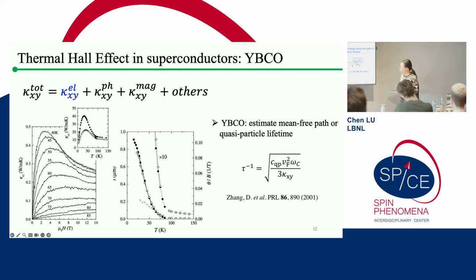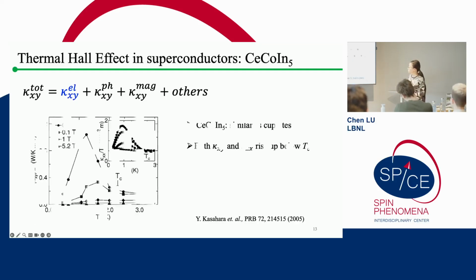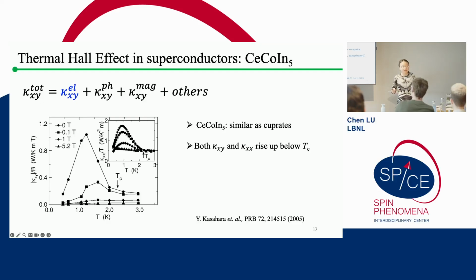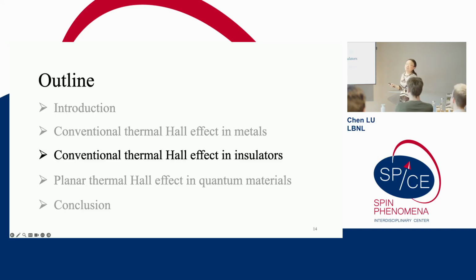And apart from cuprates, these same types of measurement have also been performed in other unconventional superconductors, for example, CeCoIn5. On the left-hand side, the big figure is the thermal Hall conductivity versus temperature taken in this material, and the inside figure is thermal conductivity versus temperature. So you can see the behavior of this heavy fermion material is very similar to what people already found in cuprates. Okay, so that was what happened like 20 or 25 years ago.